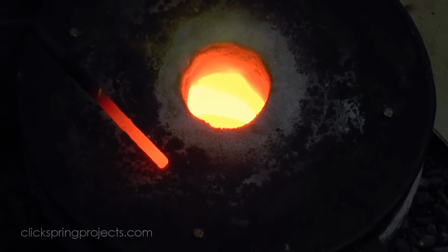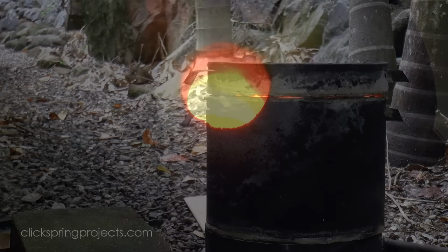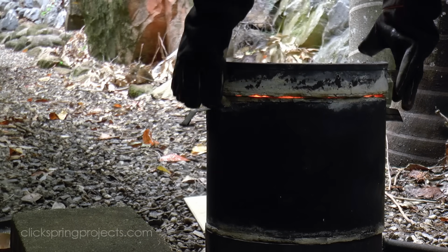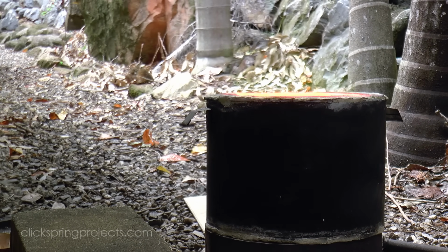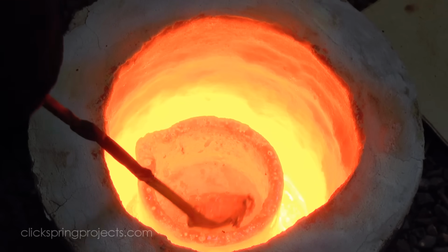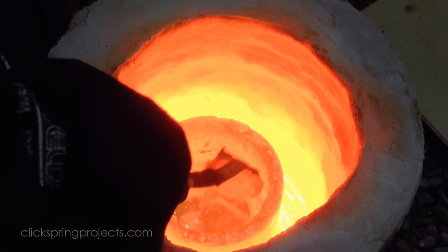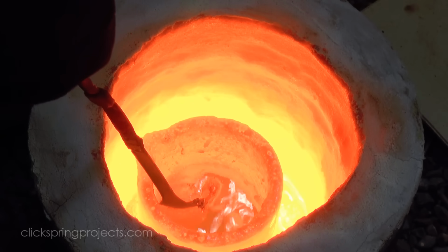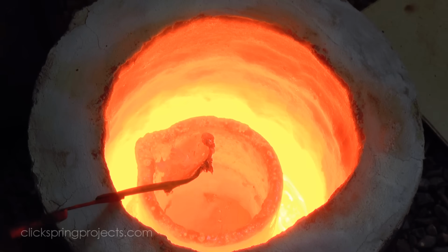A quick preheat of the pyrometer probe tip reduces exposure within the furnace when doing the temperature check later. And in normal circumstances, a light skim of oxides is usually all that's required to prepare the melt, as well as confirmation that the metal is at or approaching the pouring temperature.